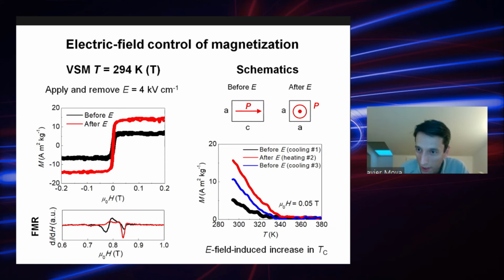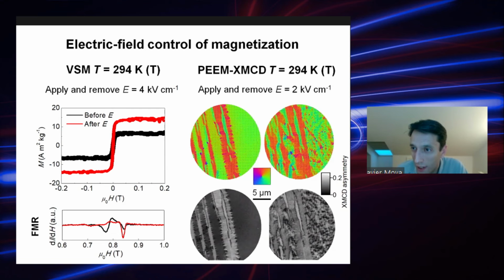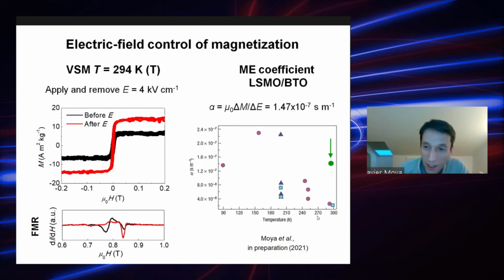So now the substrate is going to show this square pattern to the film, where the a-axis is smaller, around 3.996. So the strain change is smaller than before. And then you see that when you do this, you relax the strain in these regions, because the other region remains the same, and then you can increase the Curie point. And this is interesting because, as I said, it gives you a very large magnetoelectric effect.